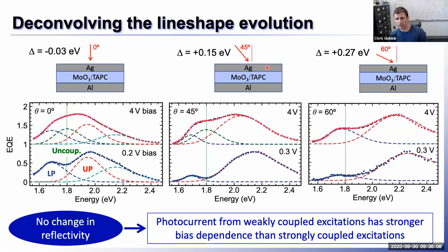So one thing that we do is we're actually performing all these measurements at low temperature. And that essentially reduces the amount of these ground state charge transfer complexes that will dissociate and gives you a much more resistive film. So I guess it's important to note that these measurements that I've been talking about so far, for the photocurrent anyway, are done at low temperature, at 77 Kelvin.